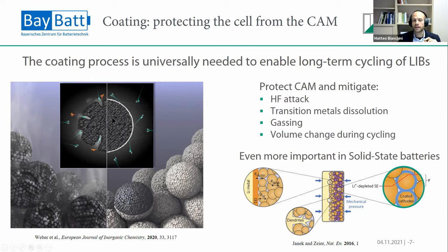And not only in the classical liquid cells, but as Professor Rupp already showed you, also in solid-state batteries. It's really even more important in solid-state batteries, because most of the solid electrolytes, especially the sulfides, have a very limited stability window. And therefore, you need to stabilize both the anode and the cathode with an appropriate coating that will allow you to have some electrochemical operation without the continuous deterioration of the solid electrolyte in contact with the cathode.